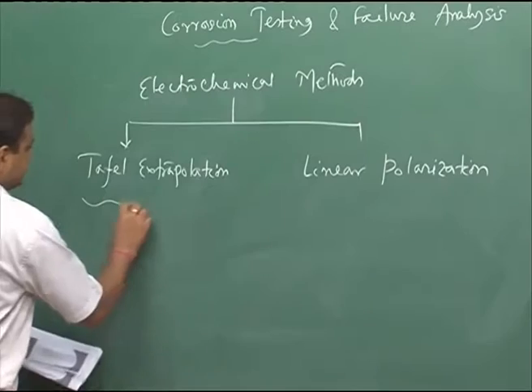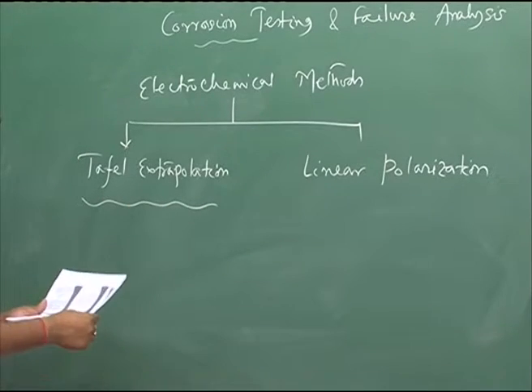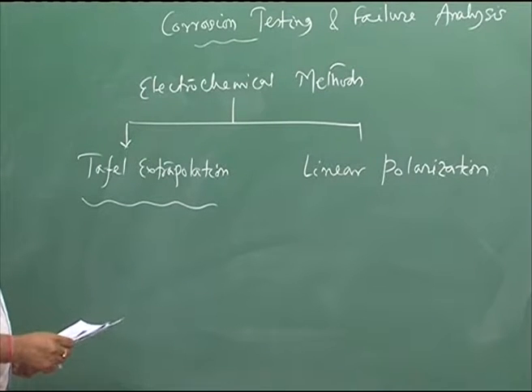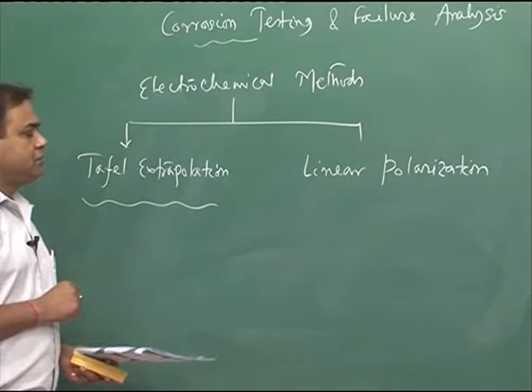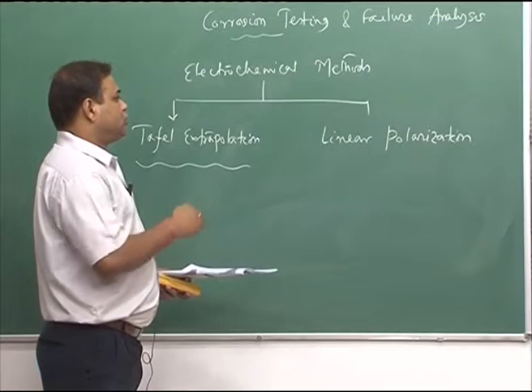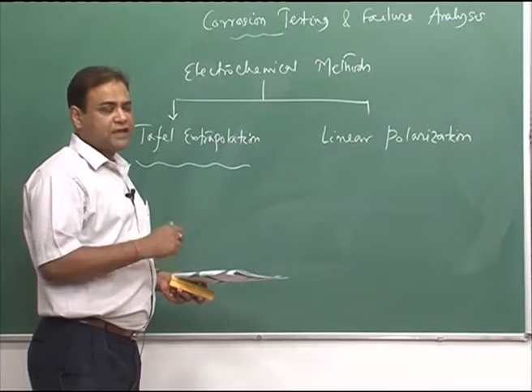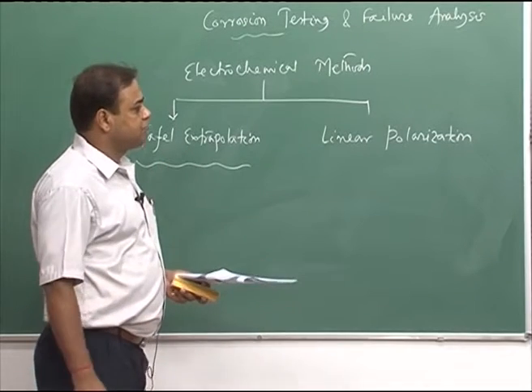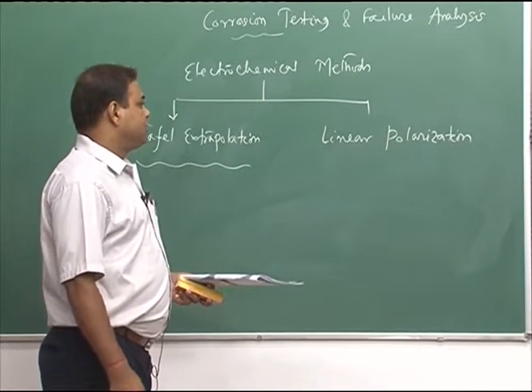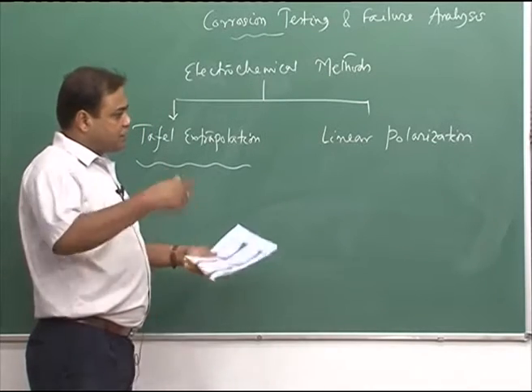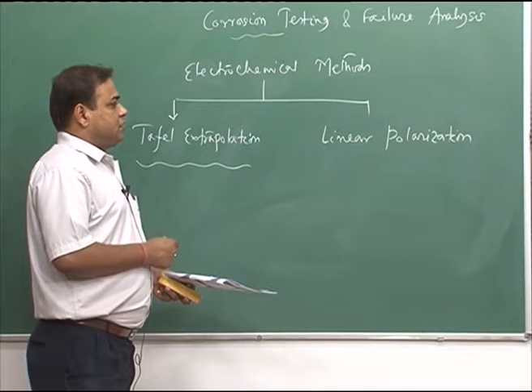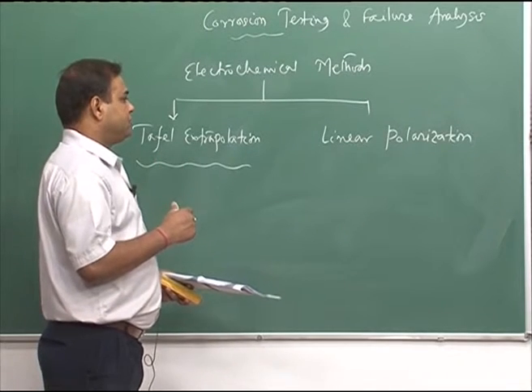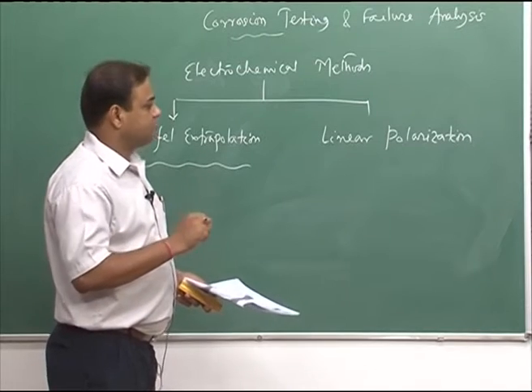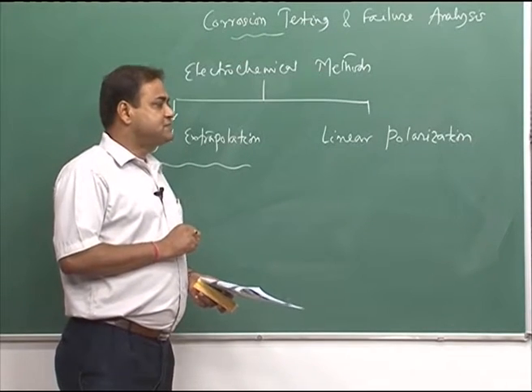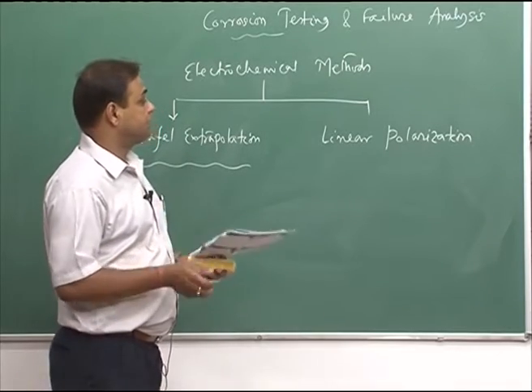Now, if we come to the Tafel extrapolation, in this method we need to polarize the sample in a particular solution or environment to the positive side as well as the negative side from the corrosion potential, free corrosion potential, and then we need to draw a Tafel slope. Where those Tafel slopes connect, that point would be the point of interest. There we can determine what is the corrosion current density at that point, and from that we can find out what is the corrosion rate.